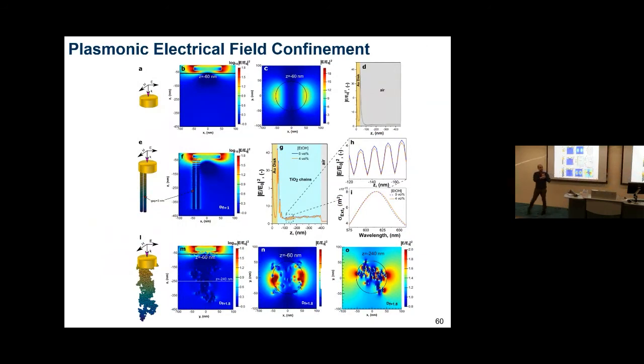Here you can see on the top only gold. Usually gold has a plasmonic resonator, a small skin depth of about 60 nanometers. This means the field enhancement after 60 nanometers goes down very rapidly. It's negligible, so you don't have an active volume anymore.